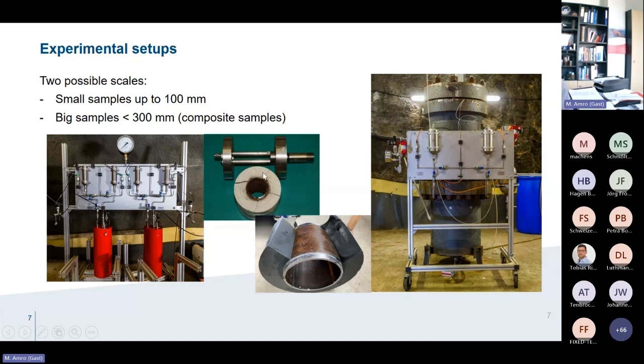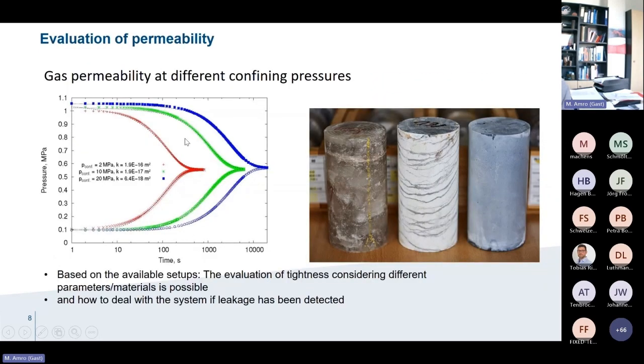But also we can consider composite samples, that means cement and casing. In this case it is coil tubing, because it's a small sample related to this equipment. But we can use also real casing samples, and we can go up to 300 millimeter in diameter. Oh, I don't have a sample here, it's too heavy, I cannot show. Anyway, we can use a reactor. Here is a reactor, a big scale reactor, and we have the same system. So we can vary any parameters you wish. For example, you give us the confining pressure, or the depth of the caverns, the gas you will consider, and so on, and the samples.